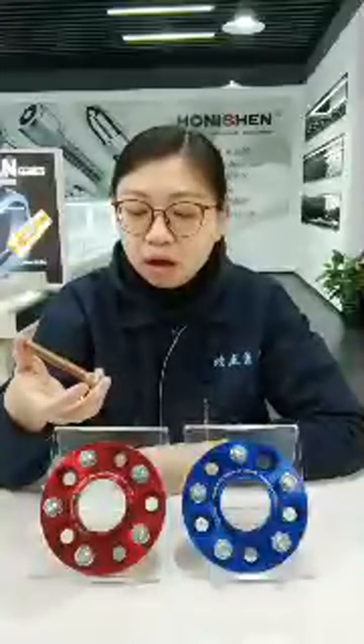Let me show you our wheel studs. Ours are made of SCM435 or SCM440, whose mechanical performance can reach the 10.9 grade or 12.9 grade. Not only the hardness, but also the durability. We refuse to use the 40Cr, which other factories always choose for wheel studs, because not only the hardness but also the durability is not enough for what wheel studs require. If it's at the hardness required for 10.9 grade, it will have the risk of breaking in your usage. So that's the reason that we always choose SCM435 and SCM440.